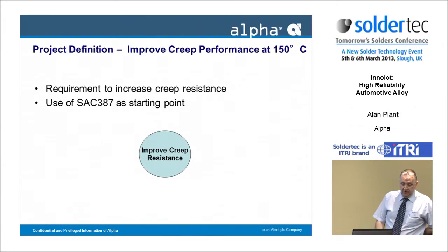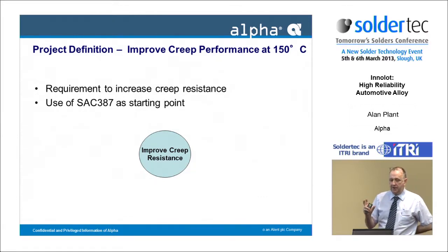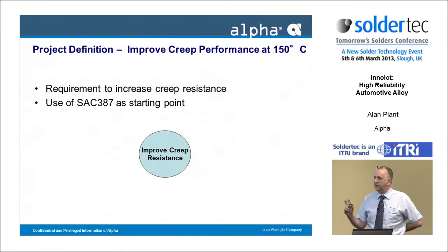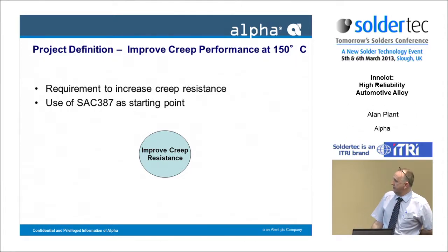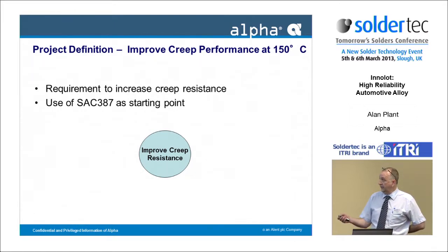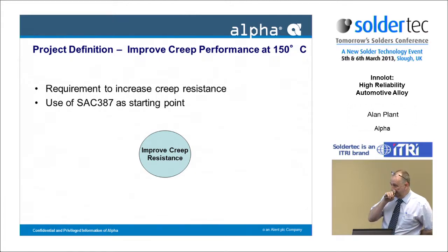So really, the project definition was how to improve the creep performance. Obviously, the thermomechanical failure being a creep fatigue interaction, but the creep part of it being considered to be the greater content. So there was a requirement to increase creep resistance, and what they did was they took a base alloy, in this case the standard SAC 387, considered to be the eutectic, or depending on who you talk to, considered to be the eutectic